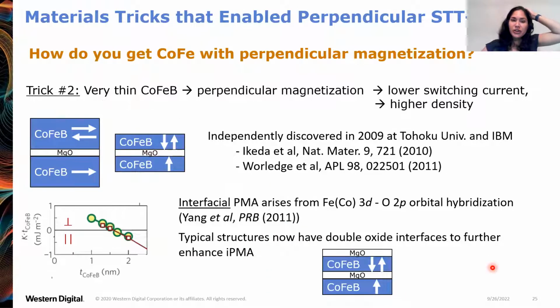The other trick I want to share addresses the question, how do you get cobalt iron with perpendicular magnetization? Because cobalt iron really, really wants to be in plane. It wants in plane magnetization. And indeed, for the tunnel junctions used in read heads, these tunnel junctions do have in plane magnetization. But for spin transfer torque MRAM, we want perpendicular magnetization. And so, this trick was independently discovered in 2009 by a couple groups and then published shortly afterwards. And the trick is to thin down the cobalt iron boron layers.